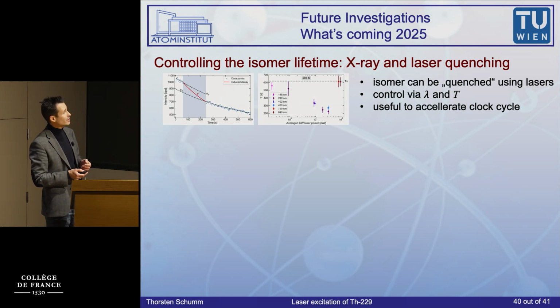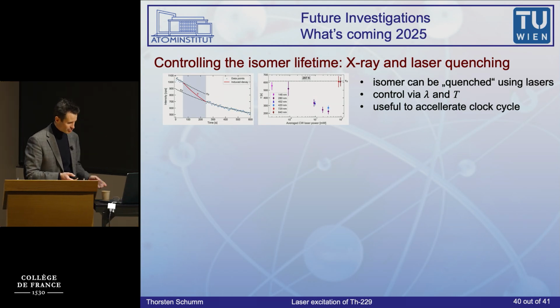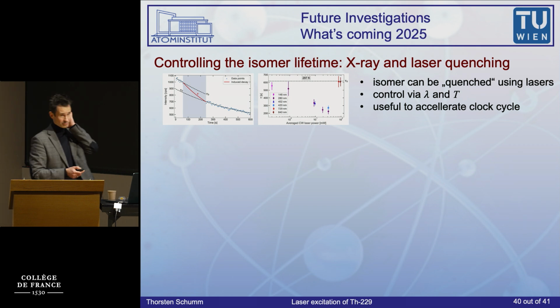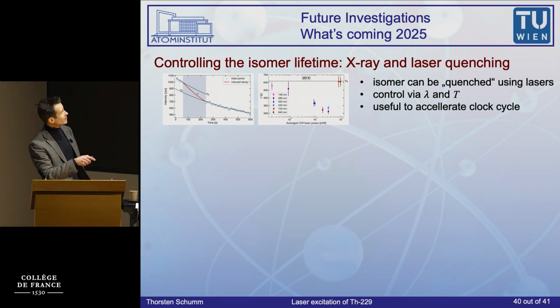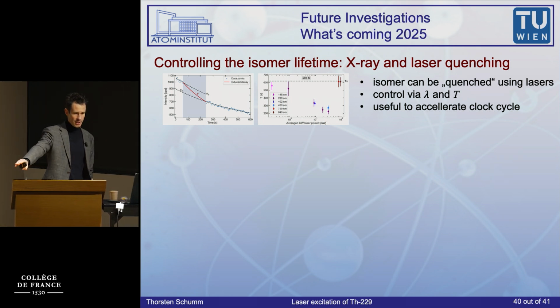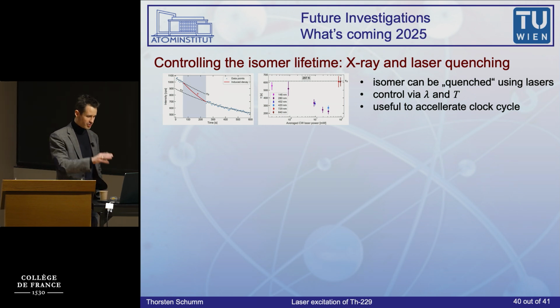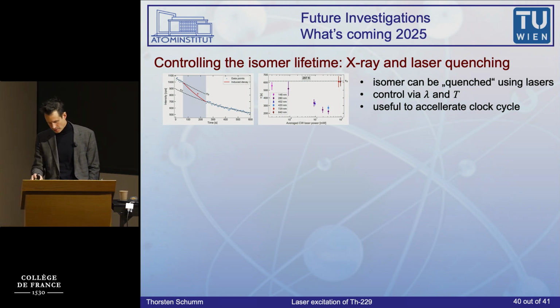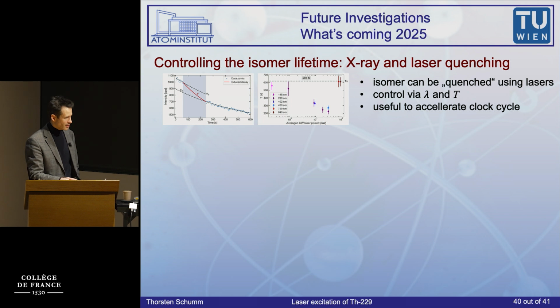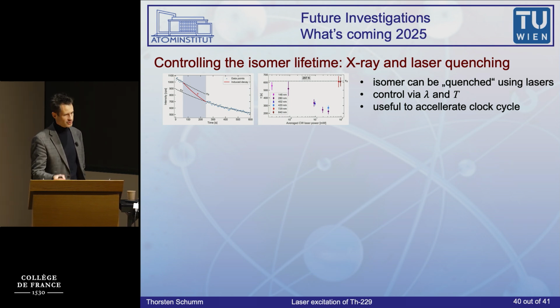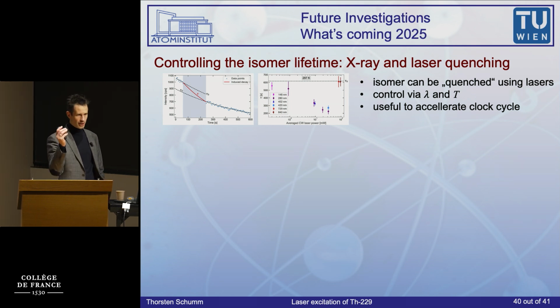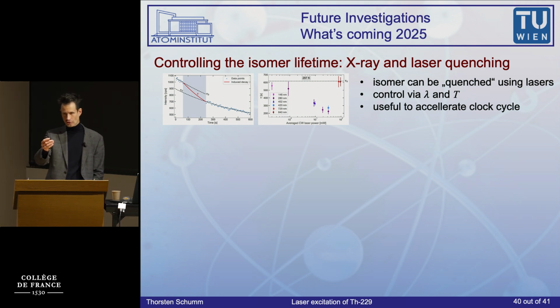So there's 3 things I would like to tell you about. The first thing is, I said there is the exponential decay of the thorium-229 in a specific material. It depends on refractive index, but otherwise it's kind of unperturbed. So it's the free photons that are raining out of this on an exponential decay. Turns out that we can manipulate the excited state lifetime by offering the system an electronic decay path.